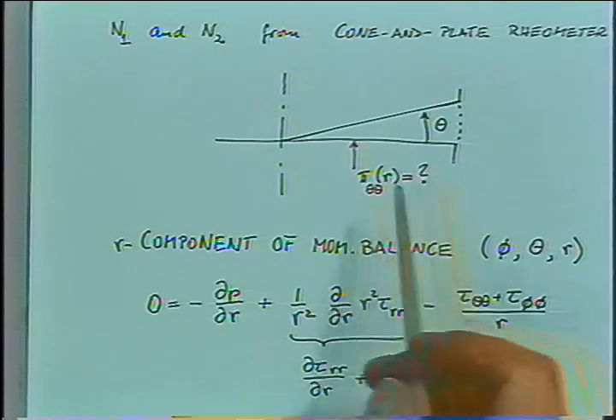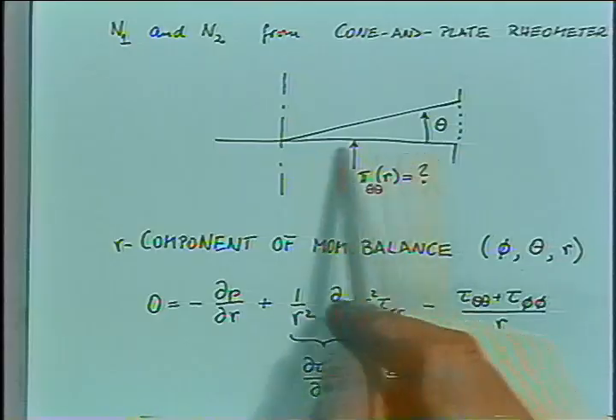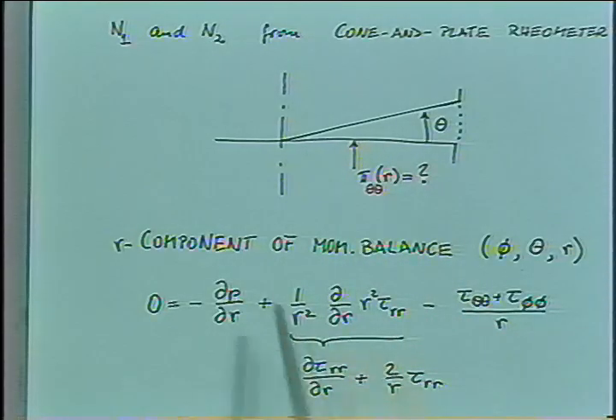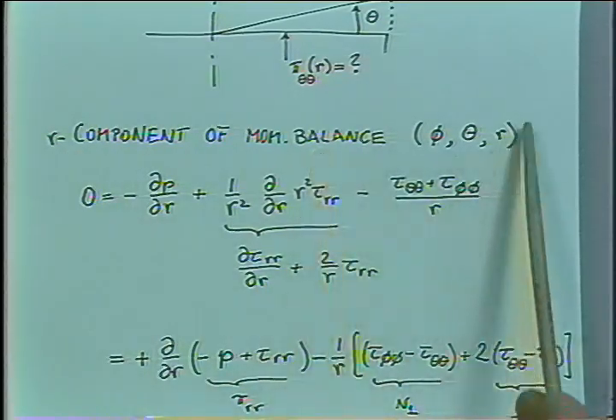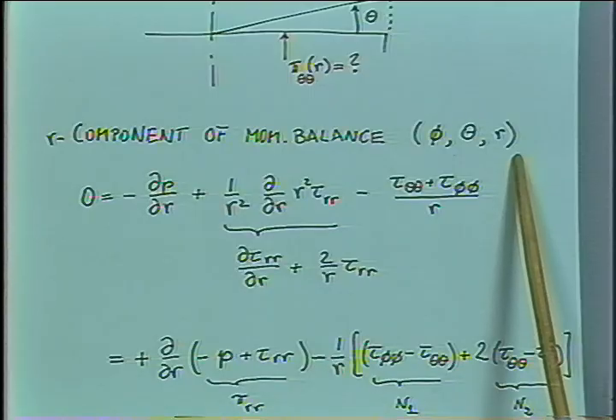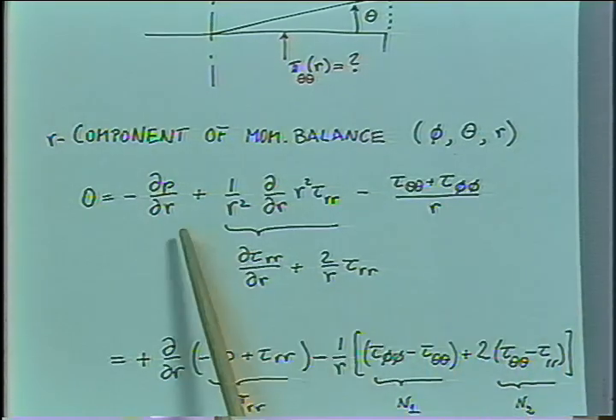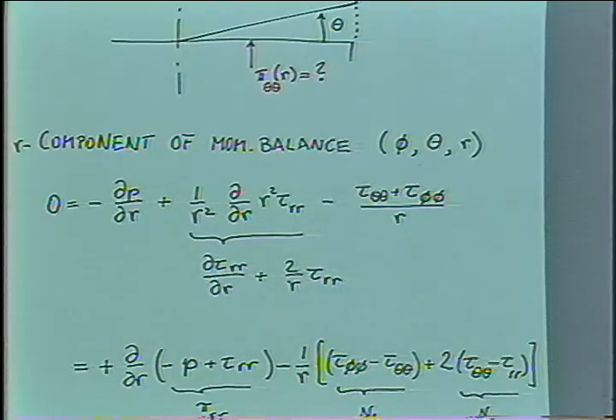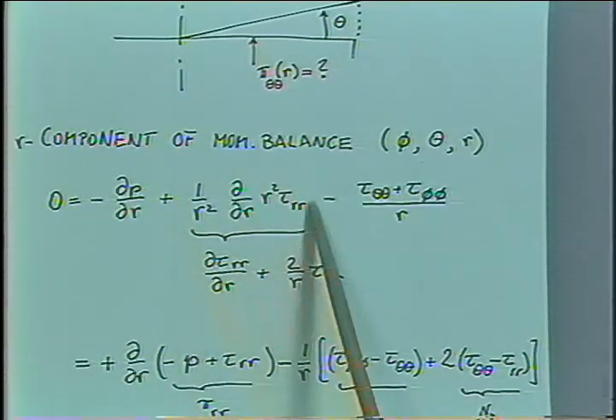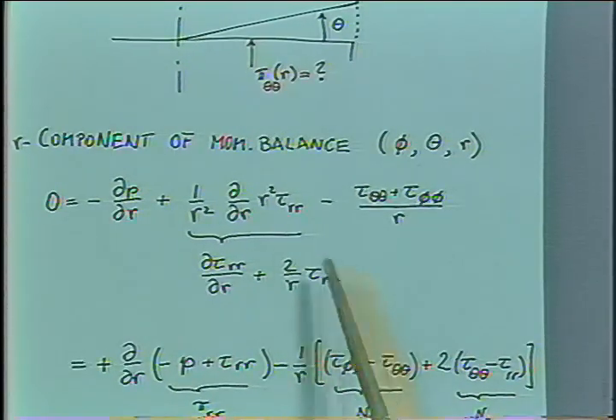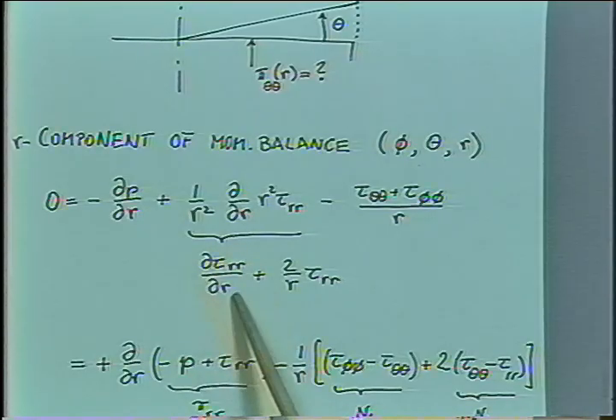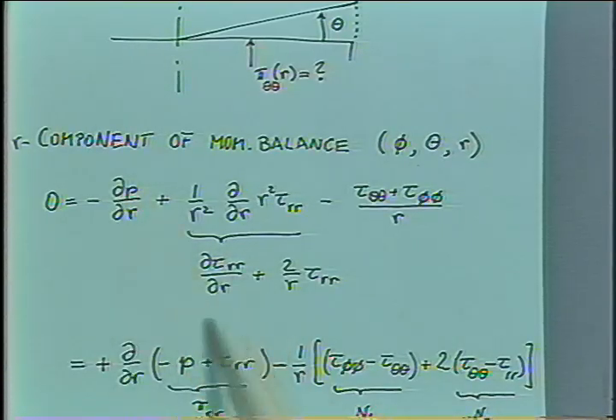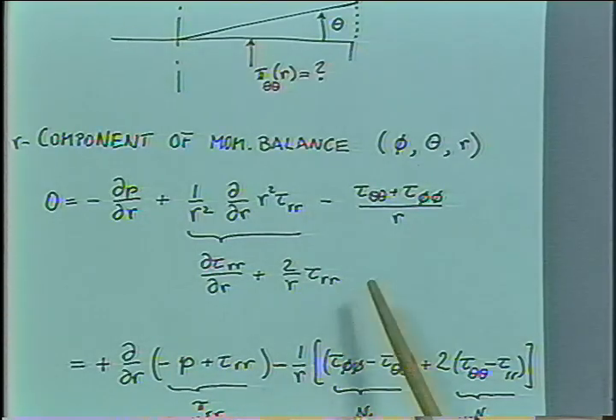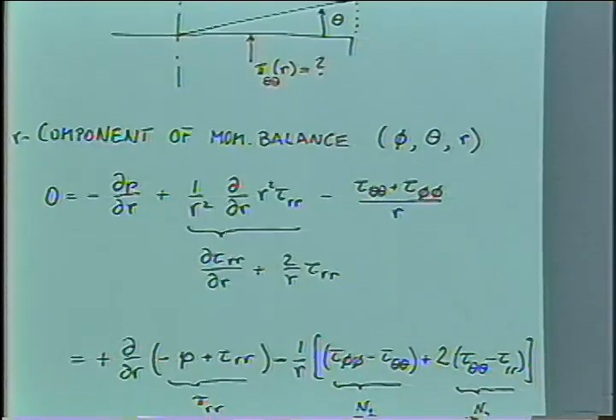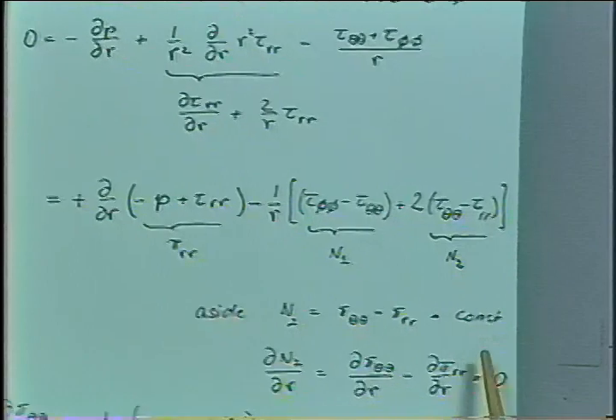Remember, the shear rate is uniform, but still the normal stress might not be uniform throughout that. It might be a function of the radius. We take the R component of the momentum balance in that spherical coordinate system. The R component is the 3 component in the shear flow coordinate system. After neglecting inertia and gravity, the equation reduces to something like this. The term, this more complicated curvature-affected term here, can be differentiated to have a gradient of the normal stress. We will combine this with this term here to get tau RR. And we combine this here with those to get an expression of N1 and N2.